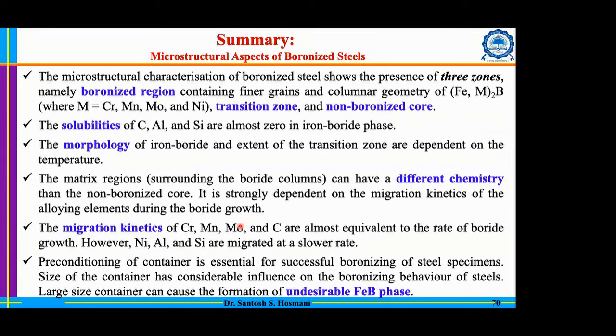And the initial study mentions that preconditioning of the container is desired here, and generally it is better to avoid the formation of FeB at the top, because that is not really advantageous. It will probably crack and get detached from the Fe2B layer.